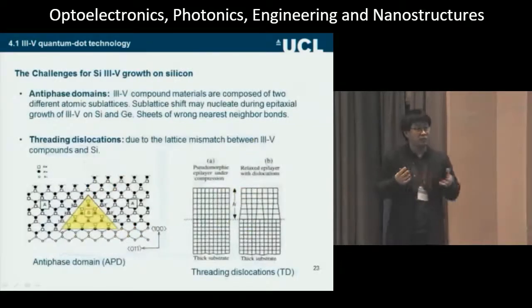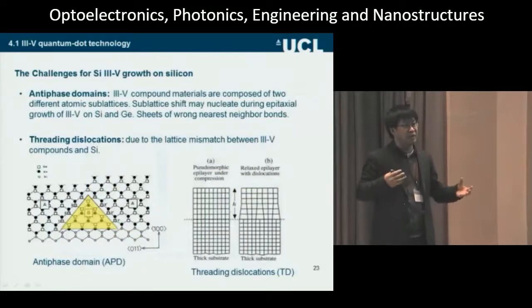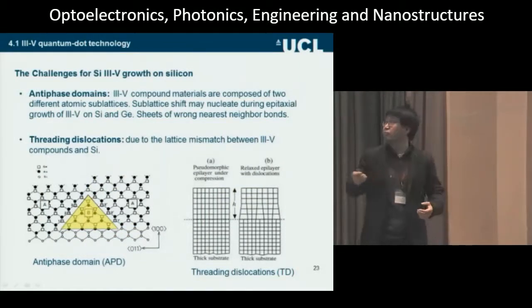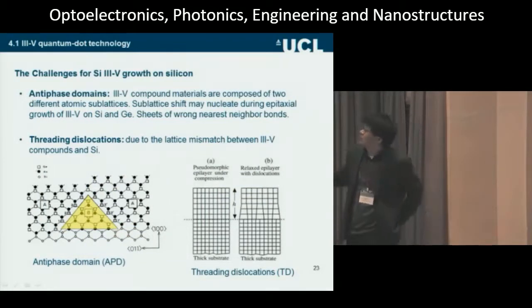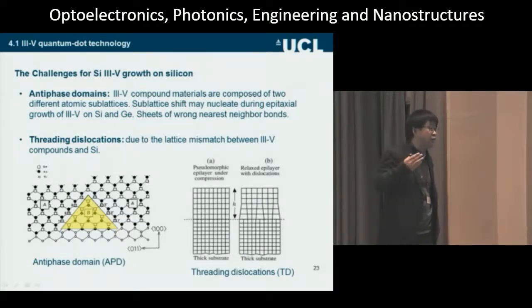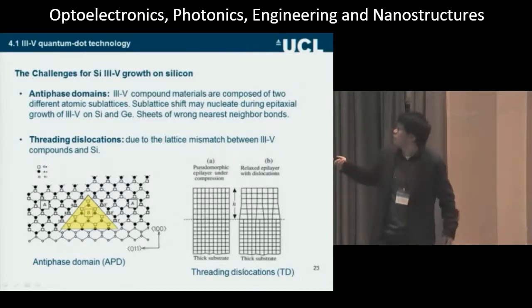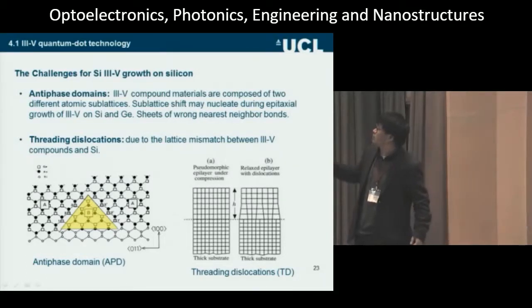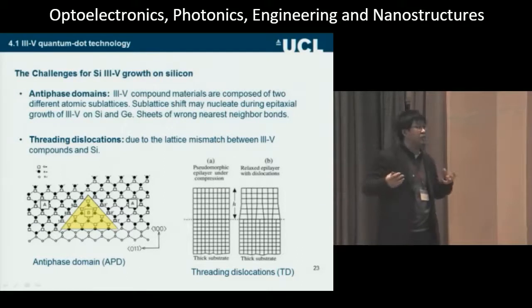Based on the achievements of quantum dot lasers, we think quantum dots are a better solution to put on silicon. But another challenge is anti-phase domains. With off-cut substrates, in the long history, we can grow anti-phase-domain-free III-V materials. Another challenge is the lattice constant difference, which gives you misfit dislocations. I'll tell you what approach we use to reduce the dislocation density.